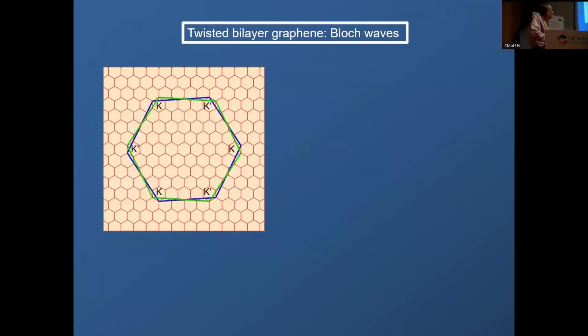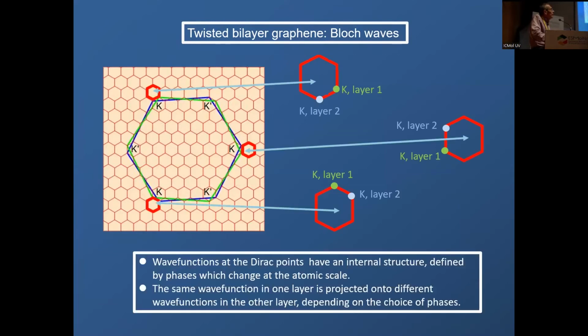And what is happening, as I'm a theorist, I would like to explain it a bit better, is that you have two very clean graphene layers, one of them rotated with respect to the other. So the electrons are well described by plane waves. And then from time to time, one of the electrons, which is moving in one layer, tunnels into the second layer. But because of the specificity of the band structure of each graphene layer, this plane wave shows up in the second layer as a superposition of 3 plane waves, not as another plane wave.